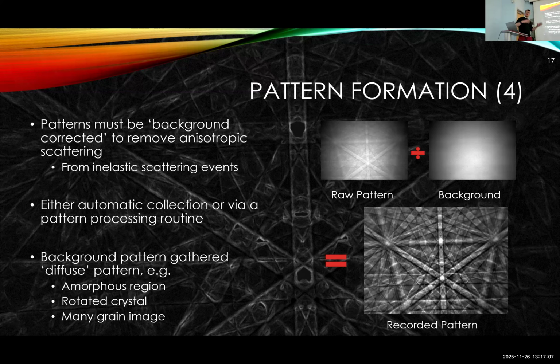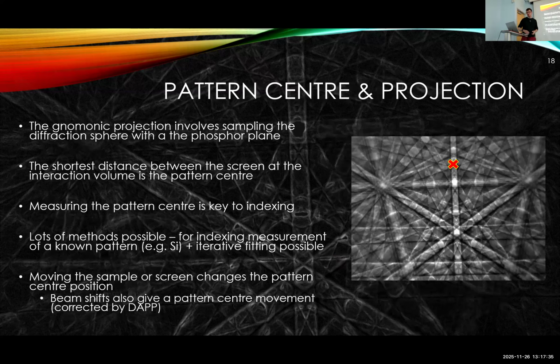To collect the backgrounds, whoever's teaching you how to do EBSD will suggest it for the particular system, but you often use an amorphous region of your sample to get the background. You might rotate the crystal while it's collecting to blur the bands. You might do something across multiple grains, or you might do some maths to remove a pseudo-Gaussian from this. So a whole range of different ways that you can solve to remove a background, and effectively flat field to make the maths easier on identifying the bands themselves.